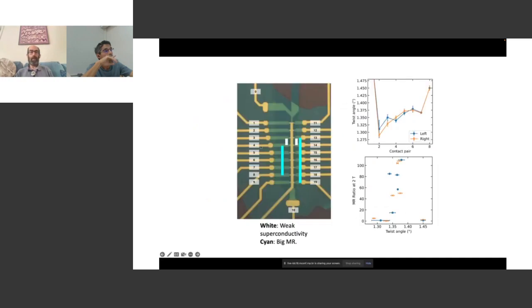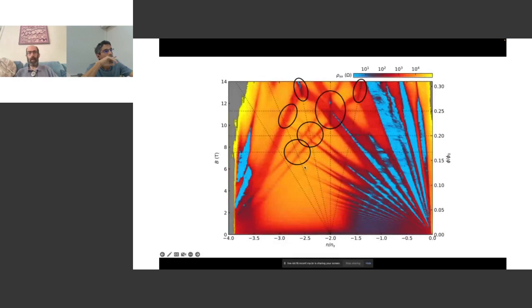Because we had a sample with many contacts and the ability to measure all of them at the same time, we could see that the twist angle is varying a little bit as we go across the sample, and this magnetoresistance seems to be occurring in a certain range of twist angle. But people had studied that range of twist angle before, and not seen those behaviors. So what was going on?